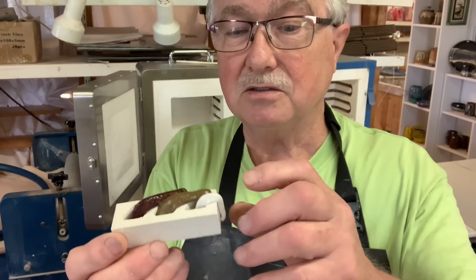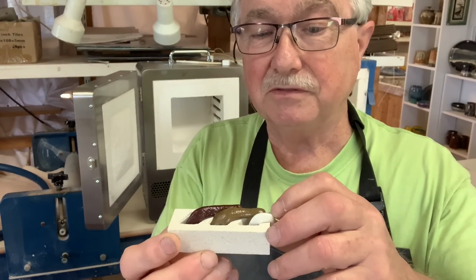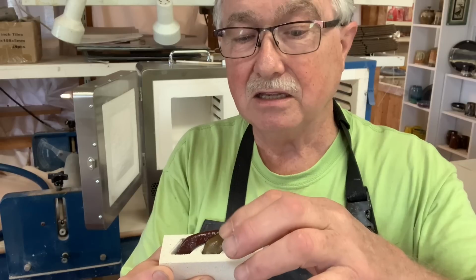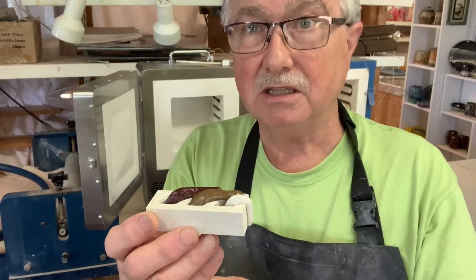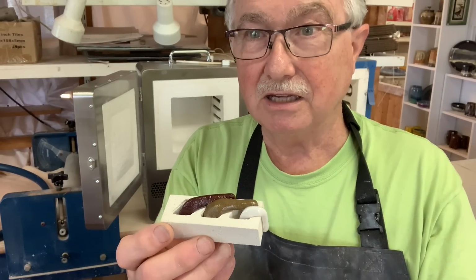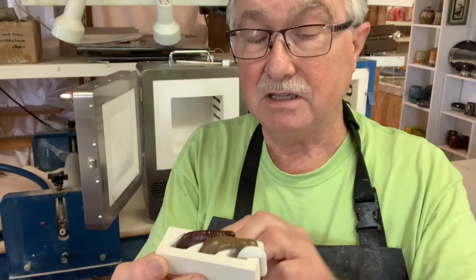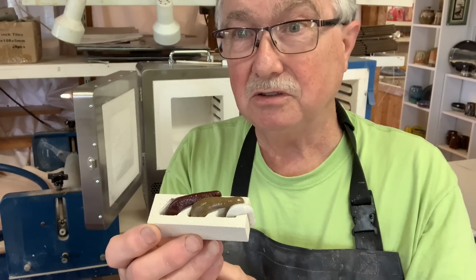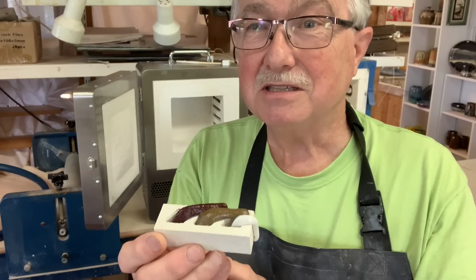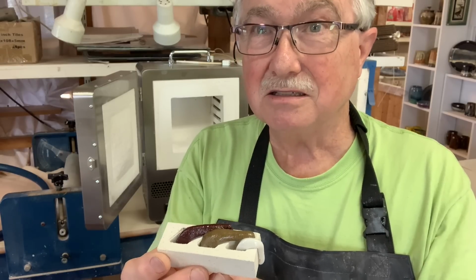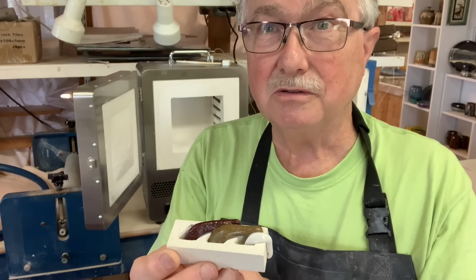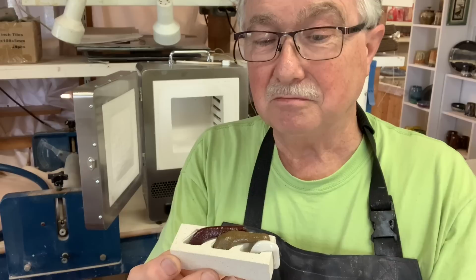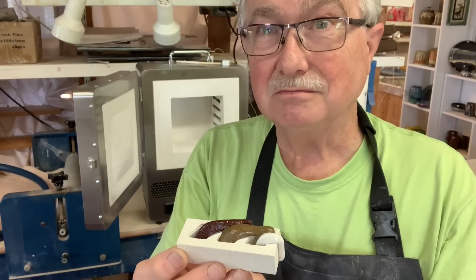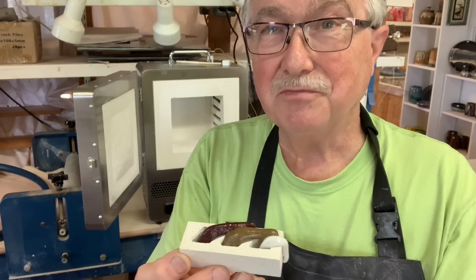Cone 6, ignore the white one, that was an old one from a different firing. Cone 6 is that, and that is melted completely. That should not be like that. Cone 5 is melted completely, and that should not be like that. But this kiln, great news, it gets to temperature easily, so you can do pottery in it. We have to work at getting the actual temperature correct.